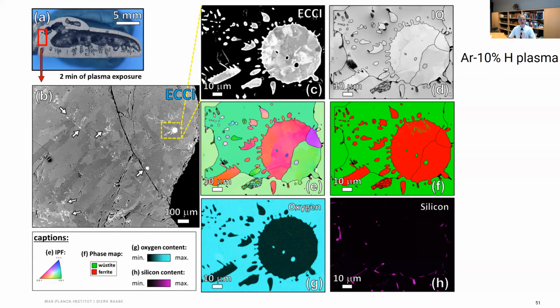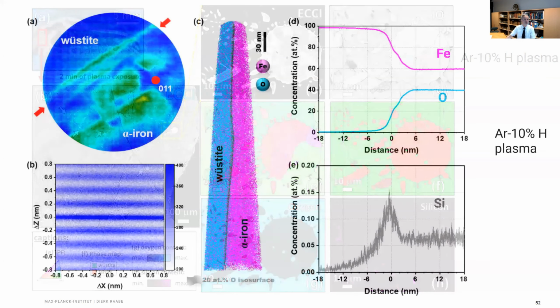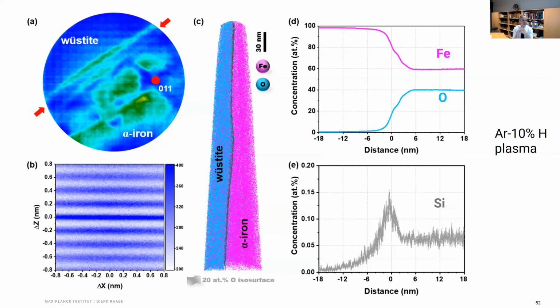And that is a very, very interesting process because you don't put all the carbon in, which you later have to take out again, and you get relatively pure iron. And again, here we zoom into the atomic scale. And we again expose these samples that are partially reduced to the atom probe. You see here on the left-hand side, atoms pertaining to the wüstite, that's the oxide. And again, these little dots are atoms. So we really go to the atomic detail here. And on the right-hand side, you see the freshly reduced iron. So you really see an interface here of this moving boundary from that plasma reduction.